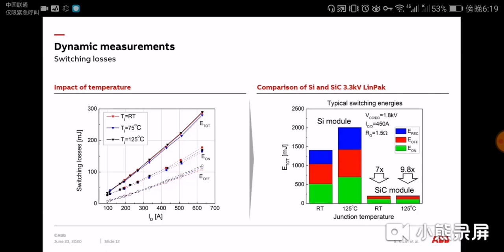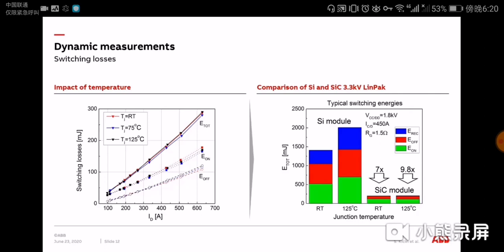As shown, the total switching losses of the silicon module were about 1410 mJ at room temperature and 2010 mJ at a temperature of 125 degrees C. The total switching losses of the silicon carbide module were considerably lower. At room temperature, total losses of 200 mJ were measured, which is 7 times lower compared to the silicon module. The difference was even larger at a temperature of 125 degrees C. There, the total losses of the silicon carbide module were about 205 mJ. This means that switching losses of the silicon carbide module were about 10 times lower compared to the silicon module. Such low switching losses of silicon carbide compared to silicon have so far typically been measured only for discrete devices and not for a high-power module.